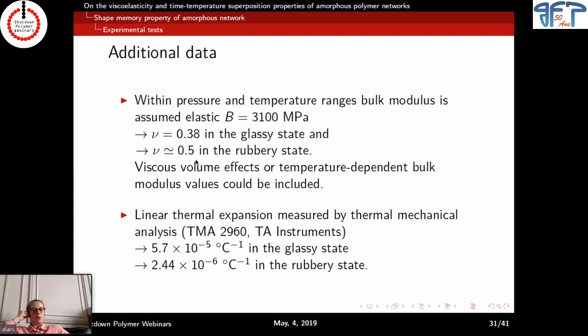But the difficult part of the Poisson ratio, which is the same for the bulk modulus, is to measure the viscoelasticity of these parameters, and it's very difficult. And we know there are very few apparatus that are doing it for the bulk modulus. Our PhD student spent 4 months at Texas Tech University. We were invited by Cindy Simon to do some measurements, and it didn't work out for us. We were unlucky that time. But what we showed is basically in what we do, change of shape, you don't have change of compressibility, and in uniaxial tension, neglecting the viscoelasticity of the bulk modulus is not really a problem.